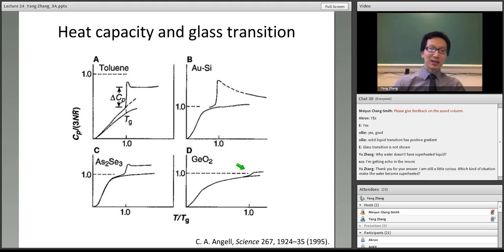a kinetically trapped phenomenon. Later on, you'll see that for the first three systems, A, B, and C, the specific heat jump around the glass transition is actually huge. But for the last one, it is small. The first three are so-called fragile liquids, and the last one is called a strong liquid. Examples of strong liquids include germanium oxide or silicon oxide. They tend to form an open tetrahedral structure, similar to ice. Okay.